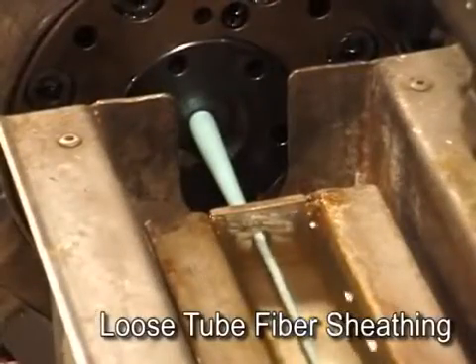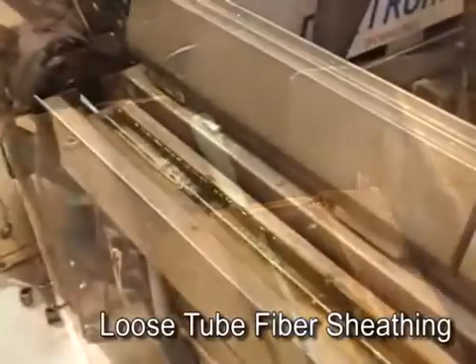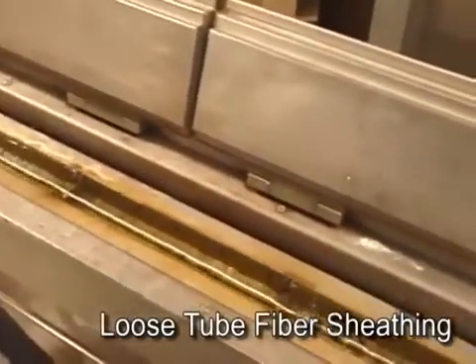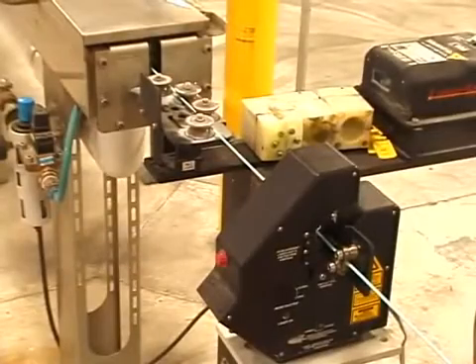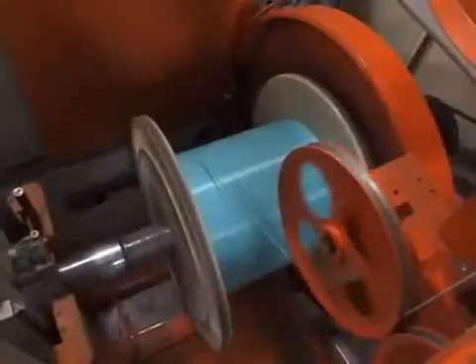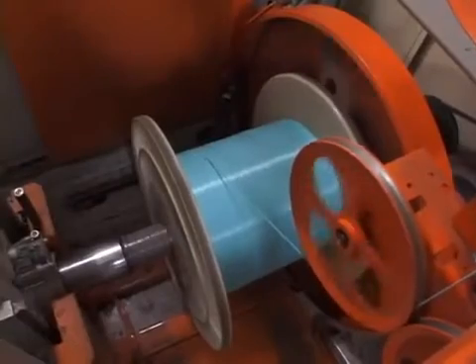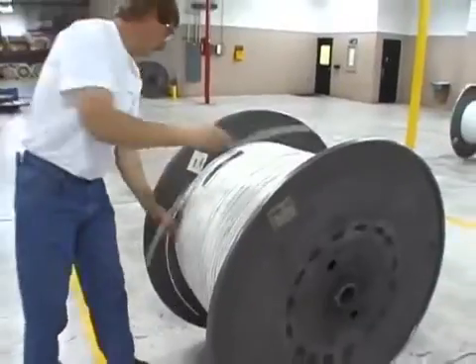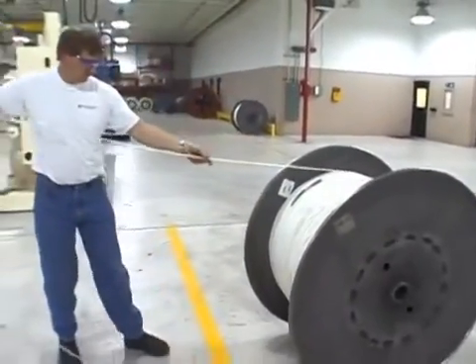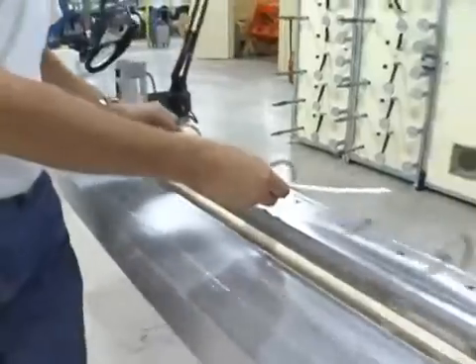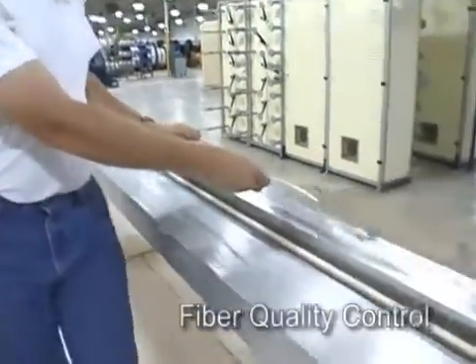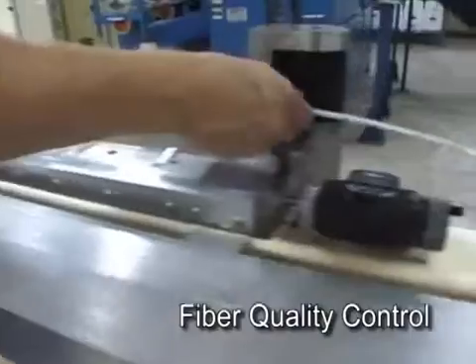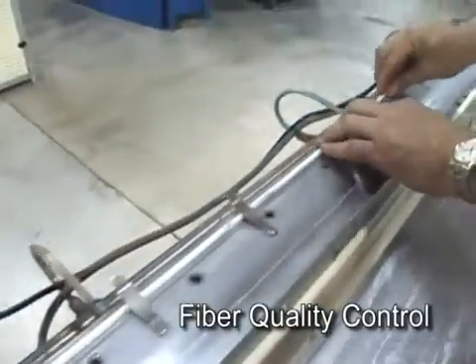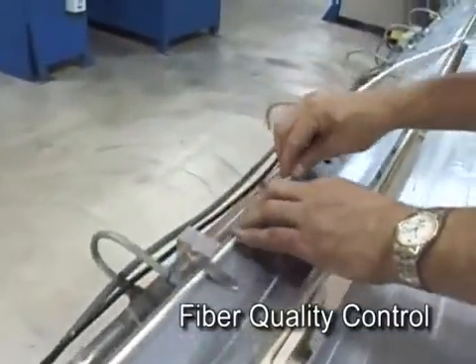Immediately upon leaving the extruder, the hot, soft tube is passed through a long water-filled trough that slowly cools and hardens the tube. The completed tube is passed through an optical micrometer to verify its diameter is within specifications. It is then wound on a take-up reel to be used later in the cabling process. As part of our quality control process, we periodically test fiber tubes to verify that there is sufficient slack fiber within the tubes. This additional fiber slack, also called excess fiber length or EFL, allows the cable to expand and contract around the fibers without causing stress or attenuation problems.